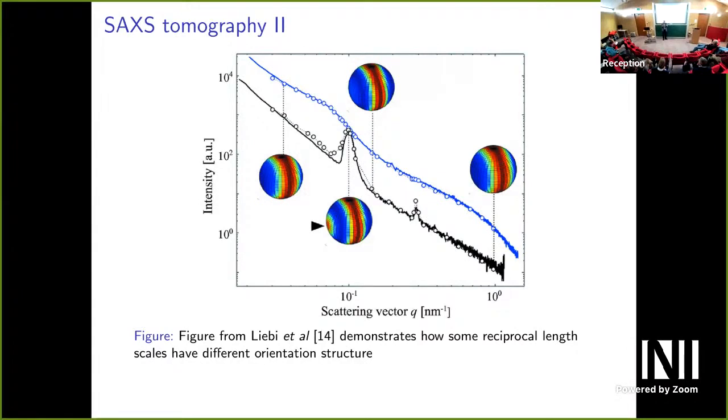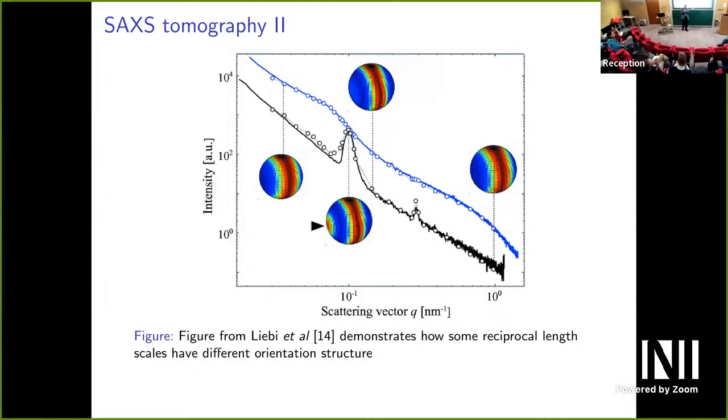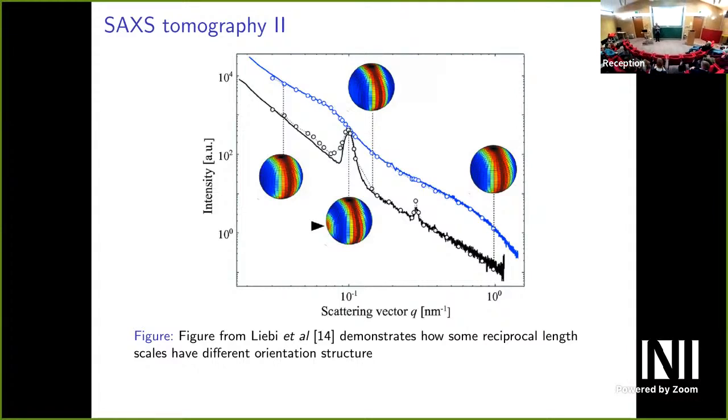In some length scales, it might have a preferred direction. So it might look like a quadratic function on the sphere, right? And you diagonalize that like an ellipse, and you have eigenvectors, and they're preferred directions of something lining up. There might be some kind of strange mixture of preferred directions. Maybe there's two things that are oriented differently, or there might be fibers and sheets and so on. And so you might get something that's not a quadratic function. And then you have to work out how to analyze that, but that would be problem specific. And it's quite an interesting question I haven't really addressed.